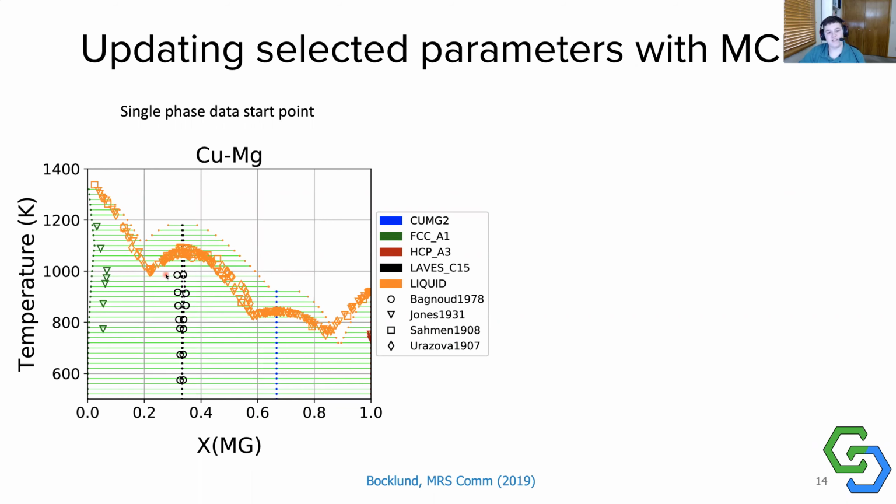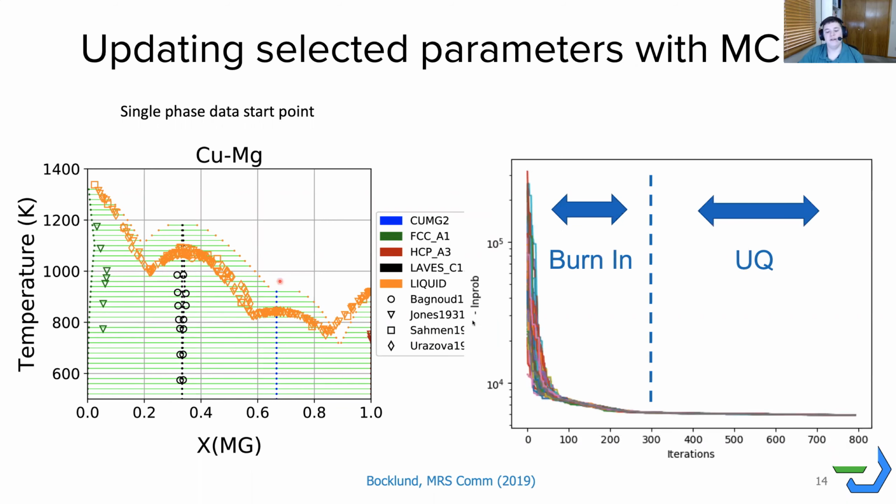And so if we perform the Markov chain Monte Carlo optimization and look at how the negative likelihood converges, in this case the negative likelihood is plotted, and so decreasing means that you're increasing your total likelihood. And so there's two phases here. There's this burn-in phase, which we'll talk more about later. But basically what's happening here is you have your starting point parameters, and those have very low likelihoods. And then as you are optimizing, the likelihood will increase and then start to level out.